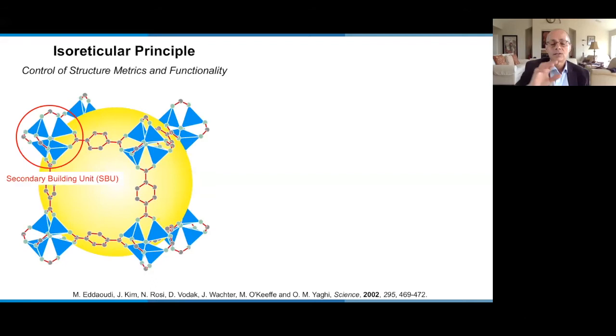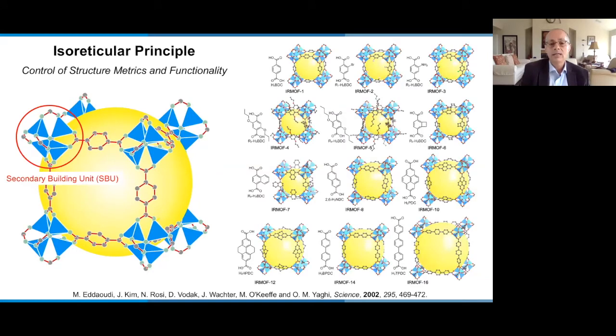Well, this SBU approach became really the standard, and until today, is the way you make MOFs. In that, if I know the conditions under which these clusters form, then I could add the linkers, different linkers with different functionalities, and even linkers that are longer. So in essence, for a solid state chemist, you can functionalize the pores and you can expand the pores. And you can't do that to a solid state material without breaking it down. But here, it is possible to functionalize the pores and expand the pores without changing the underlying topology or primitive cubic structure of the framework. So in a way, this was a way to design structures, make structures by design.